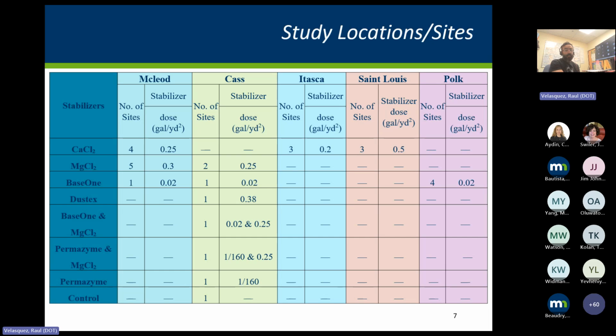Field testing was conducted on a total of 28 sites across 5 counties, so a pretty comprehensive study. The most used stabilizers were the standard ones, calcium chloride and magnesium chloride. This test matrix is pretty diverse and comprehensive, and it allows us to compare performance of these stabilizers under different conditions, different dosages, and different construction methods. That's very good because it accounts for the variability we face across the whole state.